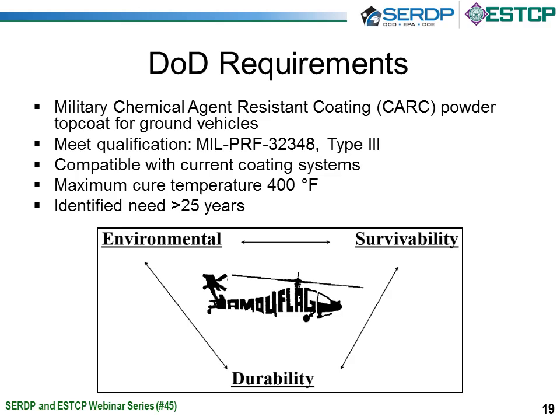So the requirements were set out in a statement of need for this product, and we are talking about a chemical agent resistant coating. So the requirements are the same as the liquid chemical agent resistant coatings. However, what had to be done was a powder coating specification was written. So the powder coating specification being MIL PRF 32348. Type 3 is the exterior top coat, which equals the existing liquid coating. So when these things are applied, ideally you cannot tell the difference between liquid and powder.